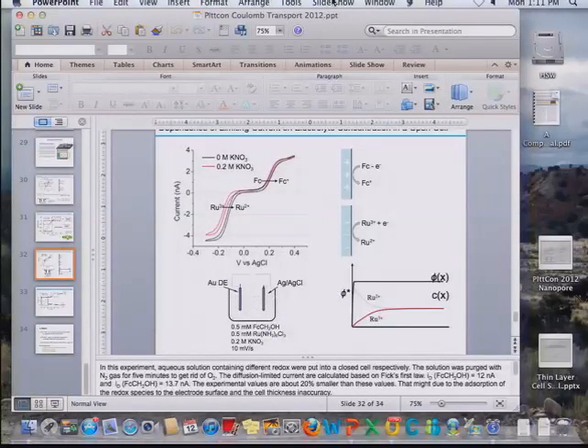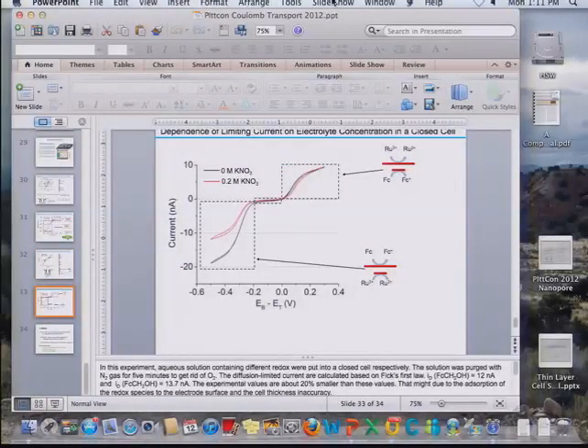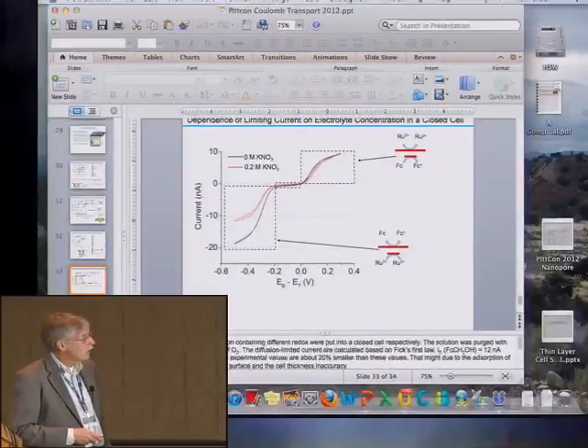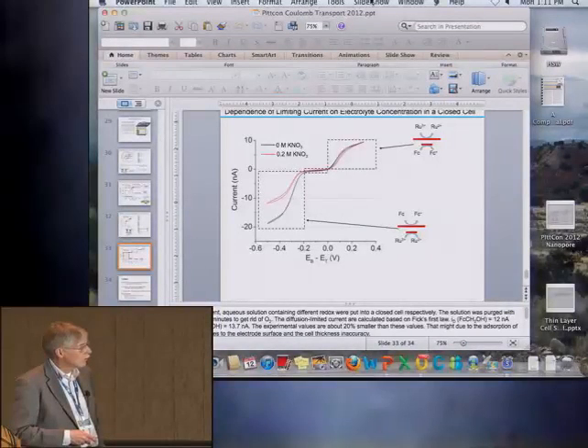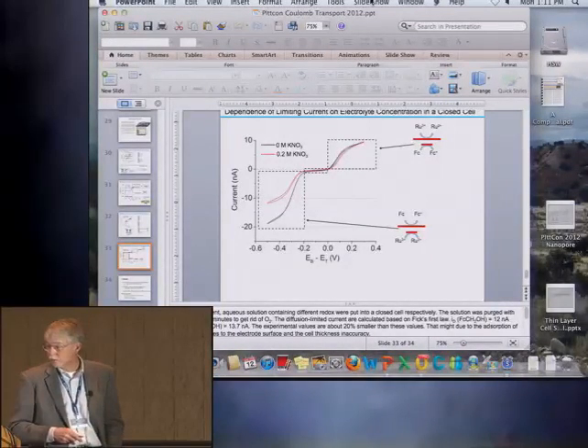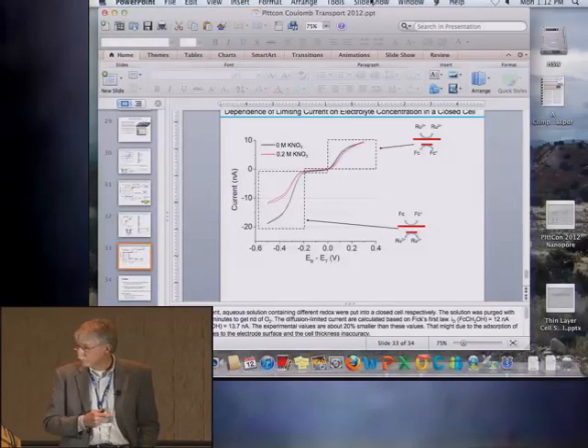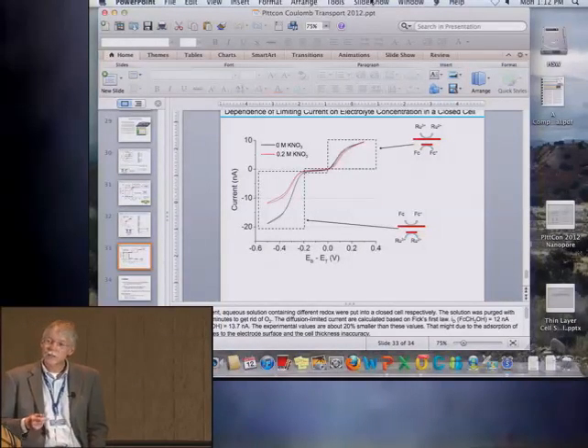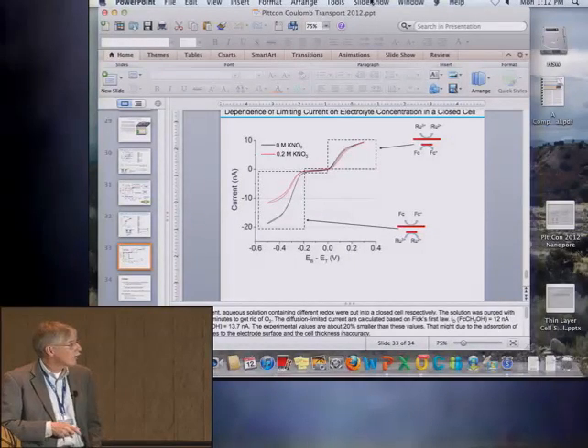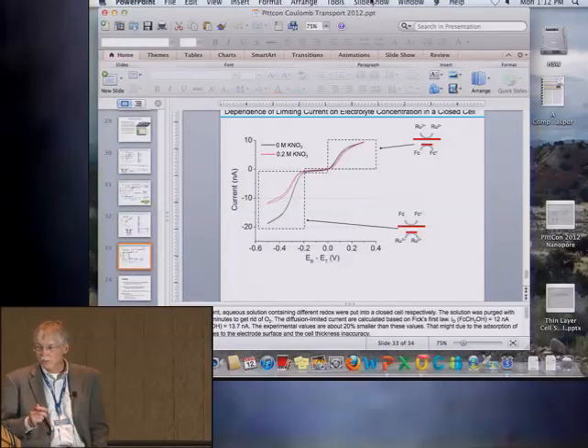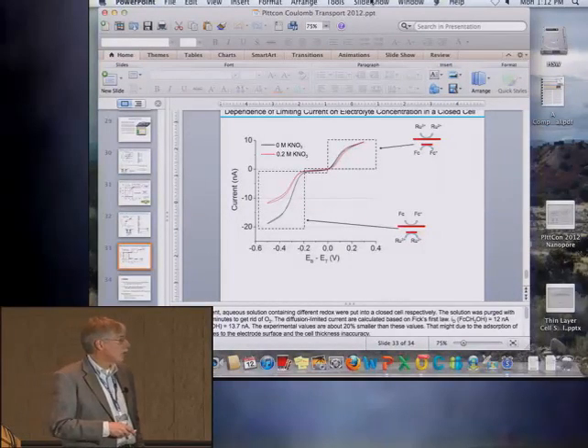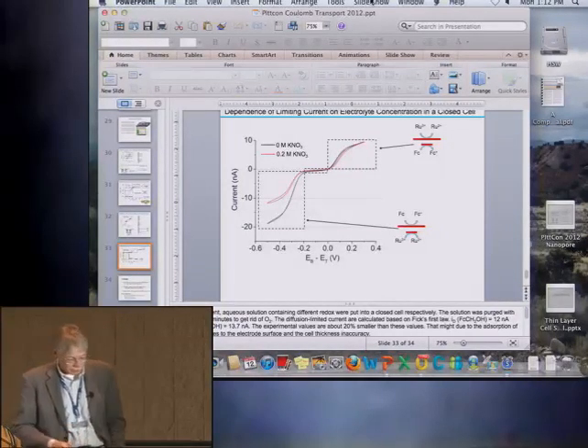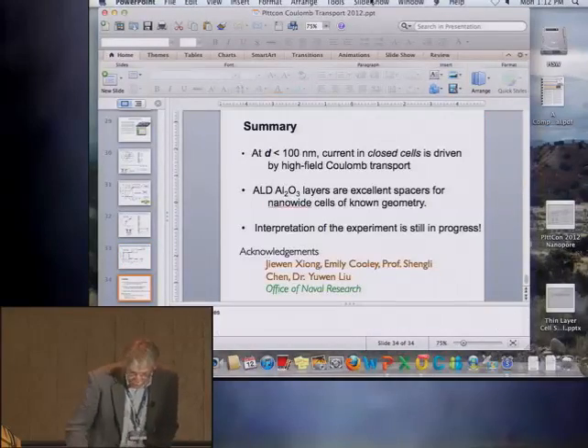Okay, so you put this in the thin layer cell, and again, you get this spectacular enhancement in the electrical field-driven transport of the ruthenium 3+ to the electrode. Instead of being about 10%, now the current doubles. It's huge, while the ferrocene stays unchanged. There's no effect on the ferrocene. In this case, the curve is not centered at 0. There's an asymmetry in both the voltage axis and the current axis. Okay, let me finish up here. Summarize.